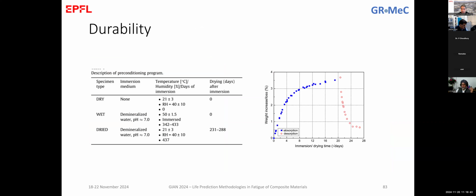So regarding durability, you remember we discussed before that composites are very hydrophilic, most of them, so they can absorb water. And imagine now that you have this adhesive system in a bridge over a river where you have a lot of humidity, so water can be absorbed. And we've seen that water in this material is saturated when it reaches around 3.5% in weight increase. So after this time, for this testing program, we also did desorption. So we tried to take water out. And then we have 3 types of specimens that you can see here as dry. So those specimens that are fabricated in the lab and were not immersed in water. We have the wet specimens and the dried specimens. So those that were saturated and then dried under a specific protocol that we followed.